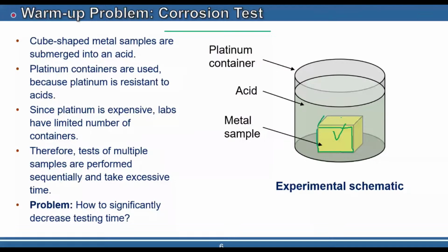They keep this sample in the acid for a certain amount of time, at a certain temperature, and then they take it out, wash the sample, and measure its weight. They measure the weight before they put the sample into the container and after. So the difference gives you the corrosion rate. Very simple system, very easy.